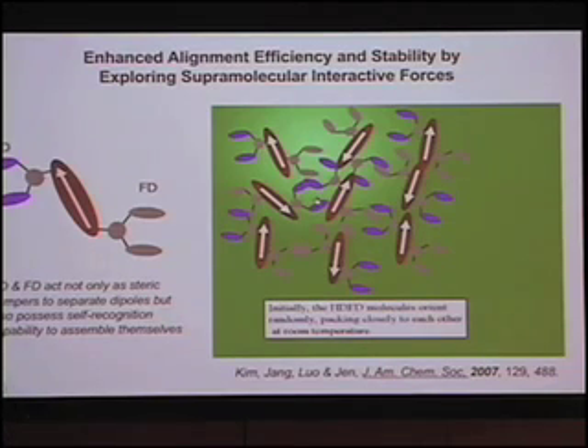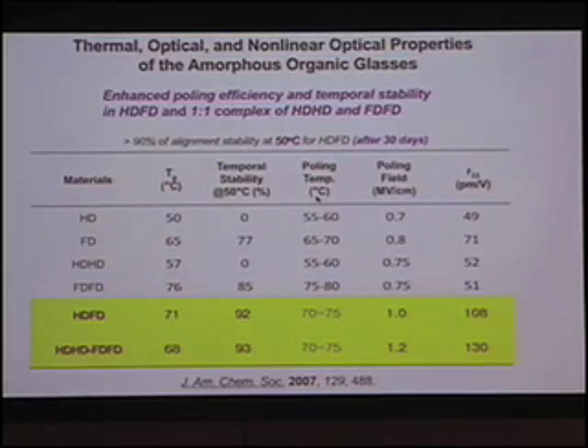Well, the movie somehow cannot work in here. So basically, you take the dipolar molecule, then you functionalize it with this dendron. Those dendrons serve a couple of different purposes. One is to separate those dipoles apart. Another one is during your heating and poling process. When you heat it up, this molecular glass can be dissociated. But when you apply an electric field, all the dipoles will be aligned toward a similar direction. When you cool down, all those self-assembling forces will start to kick in. As a result, you can form a relatively stable lattice.